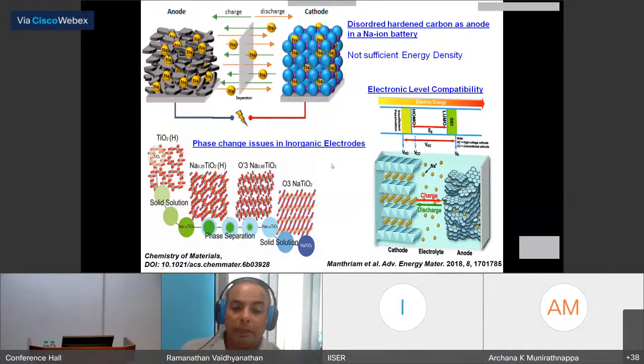And then people have come up with very interesting inorganic anodes, like titanium dioxide even can be used. But the problem with this is, as you insert more and more sodium, the structure starts to change, and the sodium insertion, deinsertion becomes irreversible when the structure changes. And also there can be volume expanded structures, which again gives the same problem that hard carbon also gives.